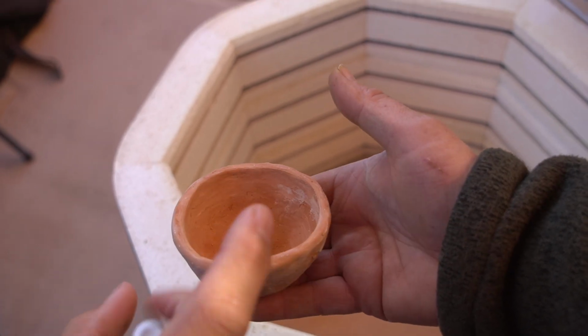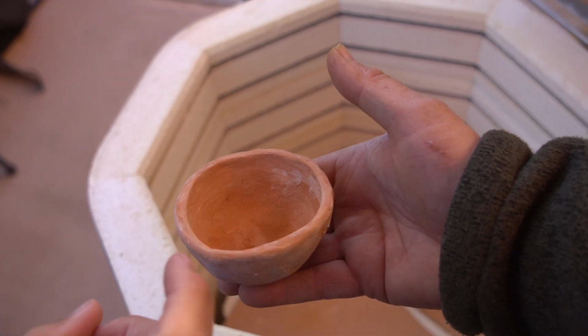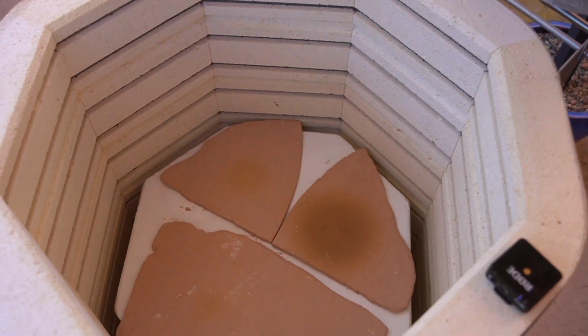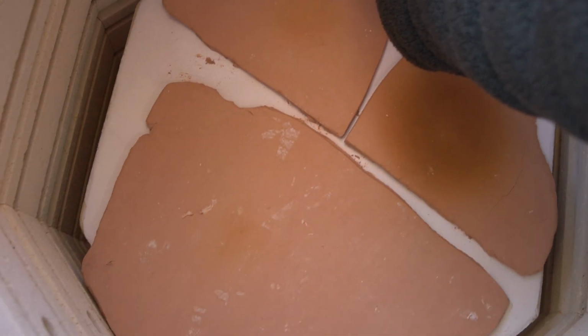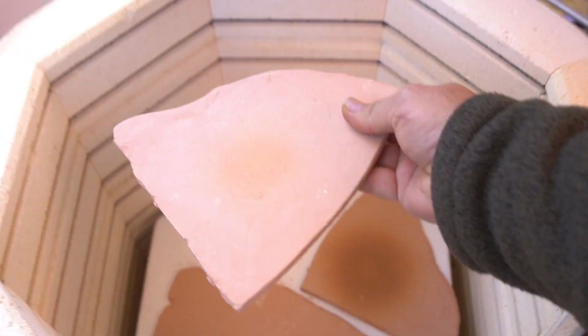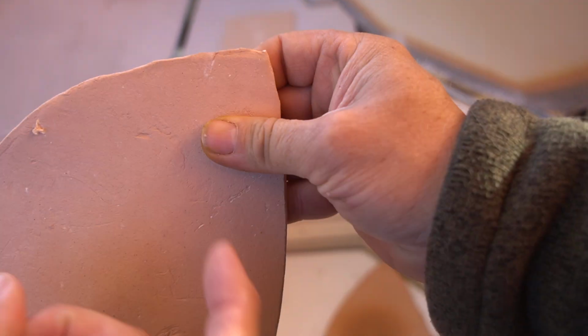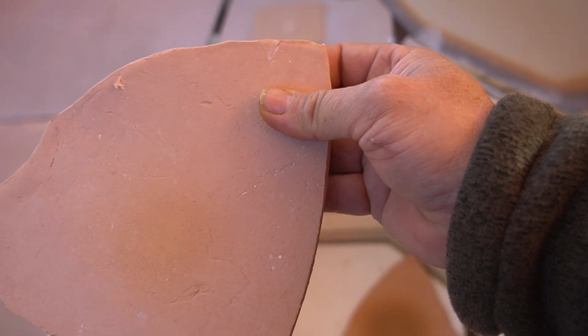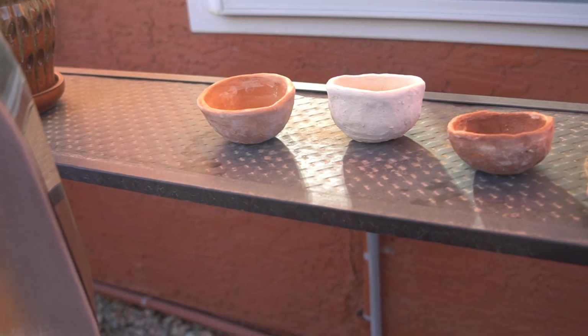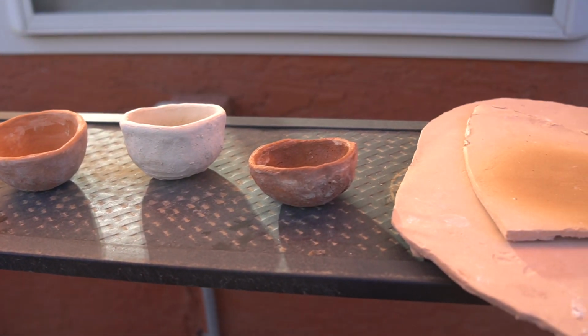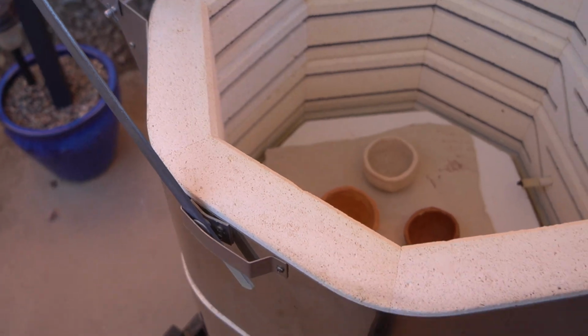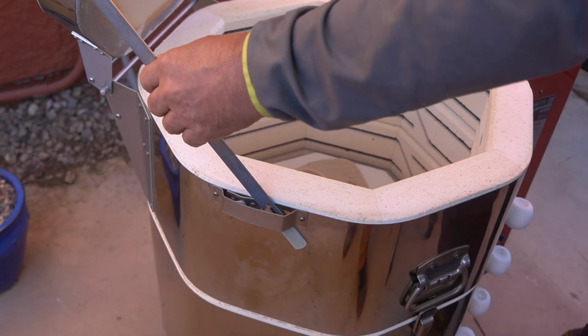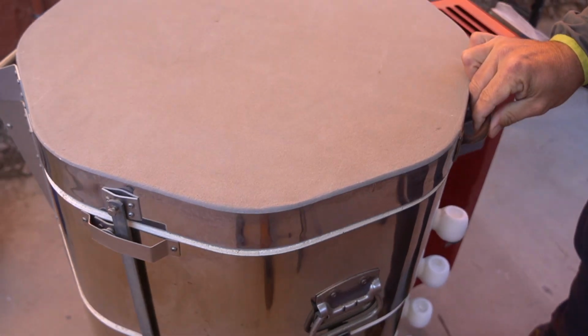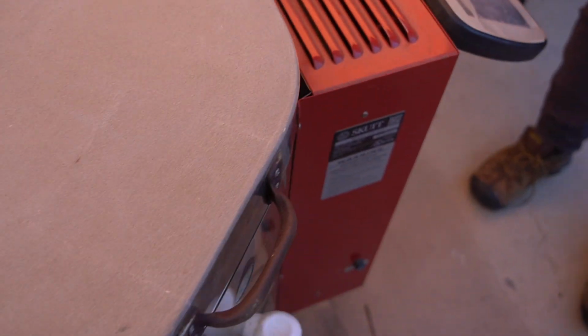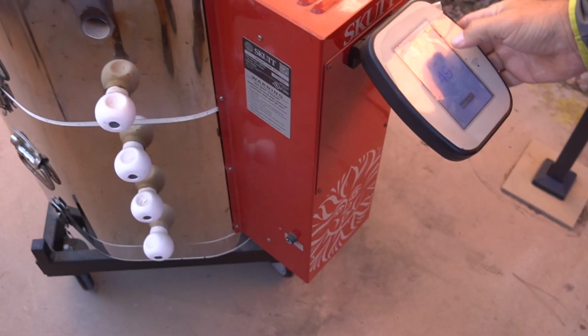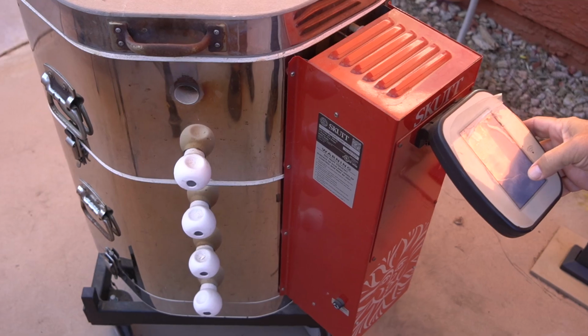All the pots were perfect. They rang really good, so I knew they were well fired. But the strangest thing to me was that none of these pots showed any evidence of being overfired whatsoever. Believe it or not, at this point I was disappointed that the pots had come out perfect. So the idea was we were going to load these up in the kiln again and fire it up to an even hotter temperature to see if we could get some sort of overfiring result. This time we fired up to almost 1,200 degrees Celsius. And again, I went home knowing that they wouldn't be done until quite a bit later.